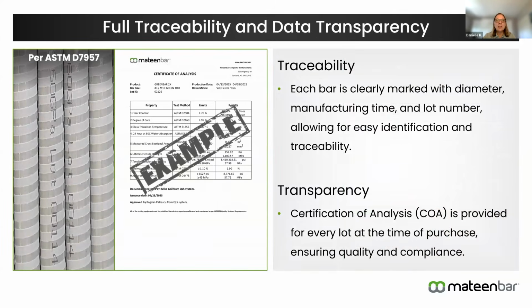According to the ASTM specification, each bar must be marked with a lot number that includes the ASTM specification to which it was manufactured, the manufacturing facility, and those details. That lot number then can be used to cross-reference with an example certificate of analysis that you see on the screen here that really outlines for each of the test requirements within that material specification what the requirement was, and then what the test results were for that actual batch or that actual lot, in this particular case, of the GFRP bar. So offering that full traceability should there be any questions on site.